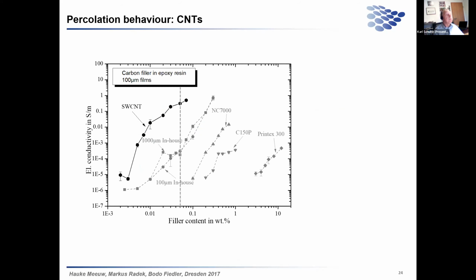We can further work on that with more modern carbon nanotubes. This is what we call single-wall nanotubes: very thin, with very high electrical conductivity. We add them to the epoxy with an extremely low filler content, in the 0.0 range, and we get a further reduction in the percolation threshold.